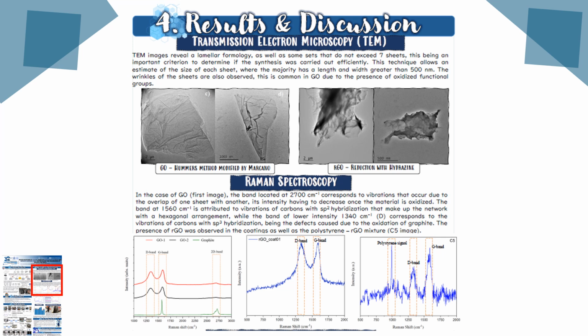In the next spectrum, we can see the RGO bands. We mainly look for the G band to be higher than the D band to initially confirm the reduction of our material. We are also continuing to work with that result to gather more information.